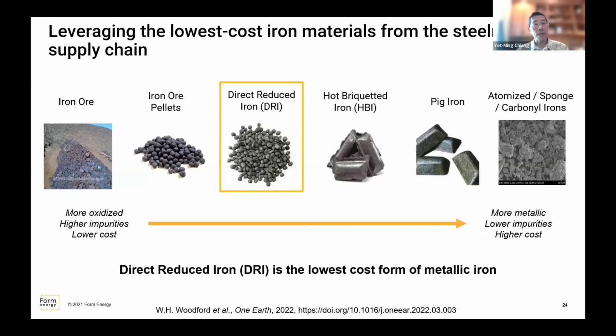From a supply chain perspective, the iron is very interesting, and what I show here is an image of the different states of iron as one goes from iron ore, which is iron oxide, which is then pelletized. Right? And then what I've outlined in the box in the middle here is the first stage in this iron supply chain where you have metallic iron. It's a material called direct reduced iron, or DRI, which is actually some 95% metallic. At this stage, that iron oxide or iron ore has become reduced in this pellet form. And this industry exists primarily to feed the electric arc furnace industry. To the right, you see some other forms of iron, but the DRI pellets here are used to feed EAF, electric arc furnaces, which are a cleaner form of iron and steel production than the blast furnaces of the past.